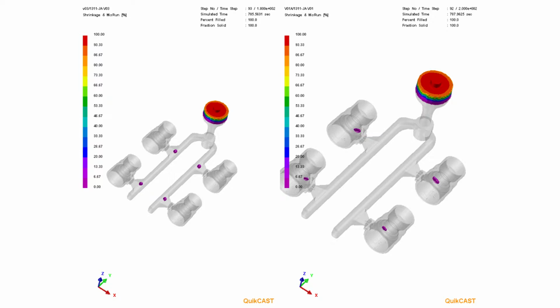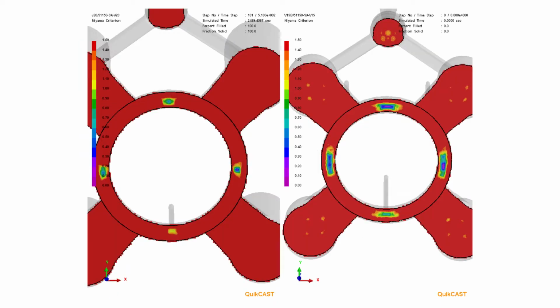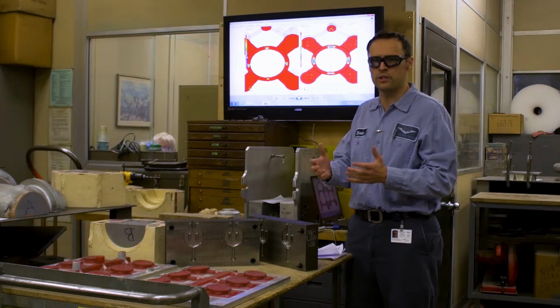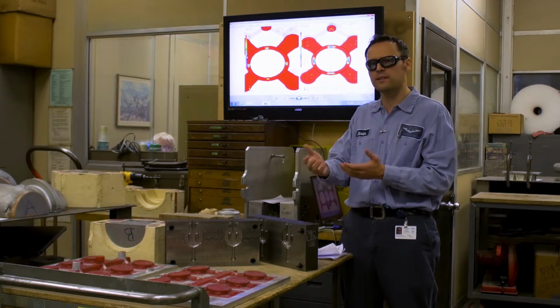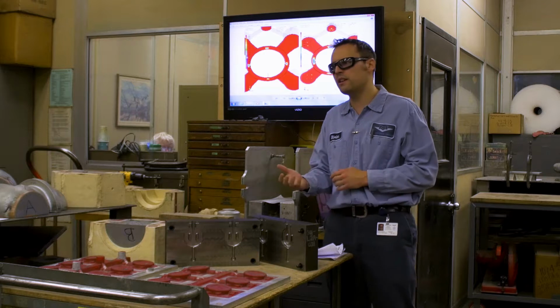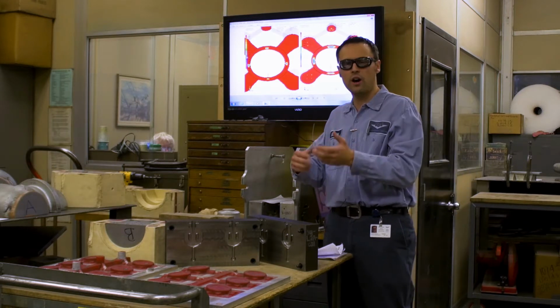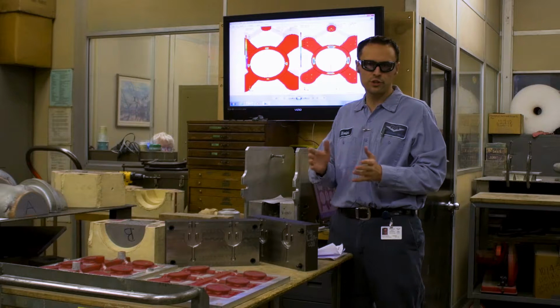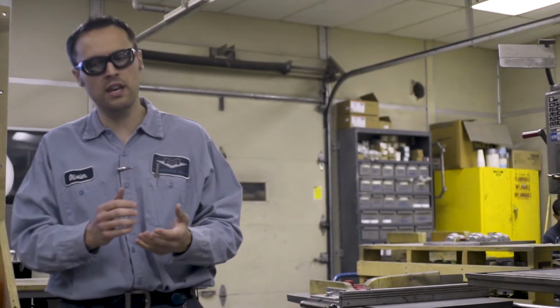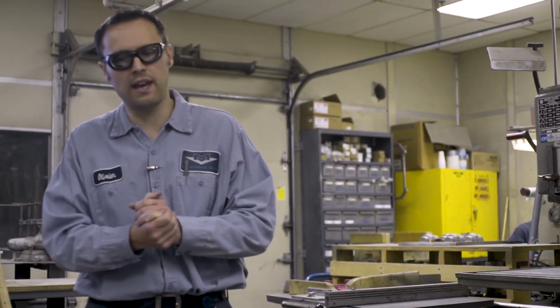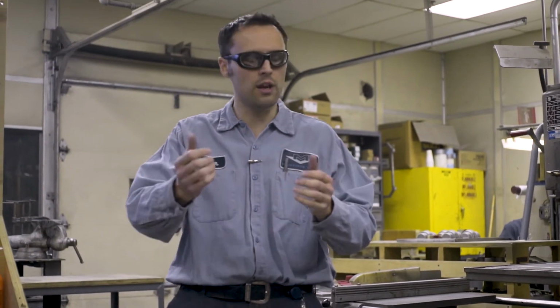So that's great. Another common defect for us in the valve business is microporosity. Here we pressure test all of our valves, and we also pressure test most of the components that go into the valve. And sometimes you have a casting that's machined and it looks great, and you pressure test it and it's leaking, or there's a little water weeping when you pull it off the test fixture, and that's not good. So essentially you look at it with your naked eye and you cannot see anything, but you have that water weeping out, and that's due to microporosity in a lot of cases.